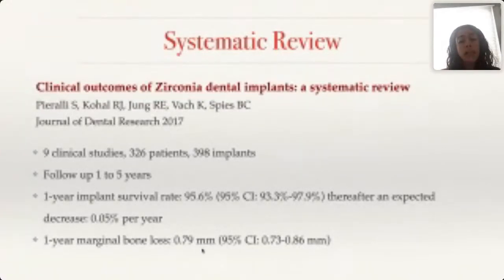This systematic review contained 9 clinical studies, 326 patients, 398 implants, with follow-up of 1 to 5 years. Their 1-year implant survival rate was 95.6%, with a decrease of 0.05 per year after that. 1-year marginal bone loss average was 0.79. So there are some more clinical studies, but it is very limited.